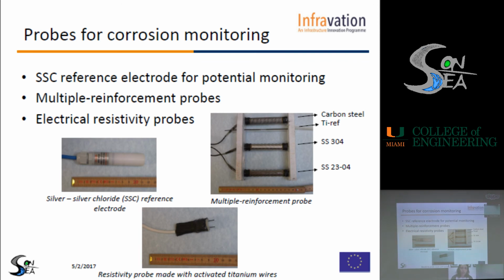The aim of our activity is to monitor the corrosion conditions of the reinforcement in order to detect the possible initiation of corrosion in time. And to do this, we used different types of probes. First of all, we used a reference electrode of the type silver-silver chloride that is used for potential monitoring.